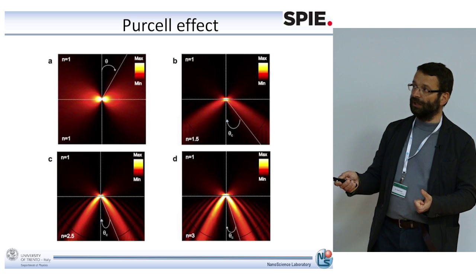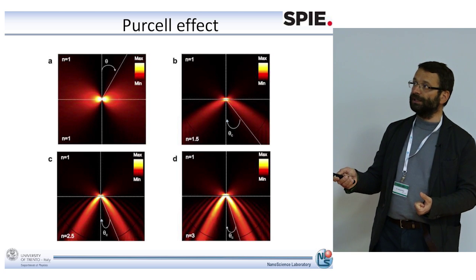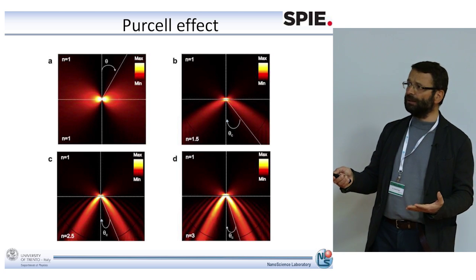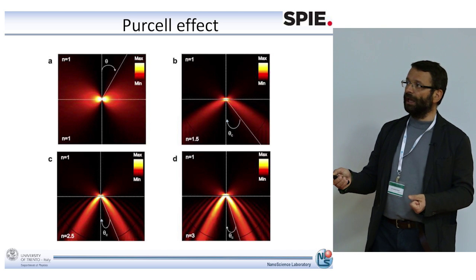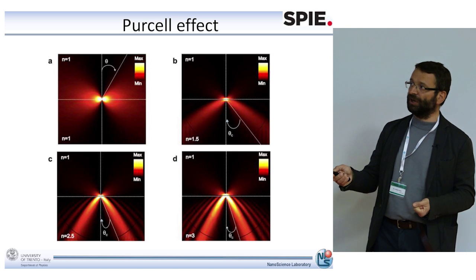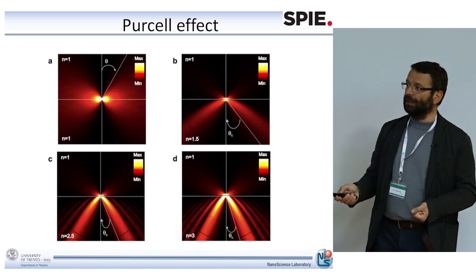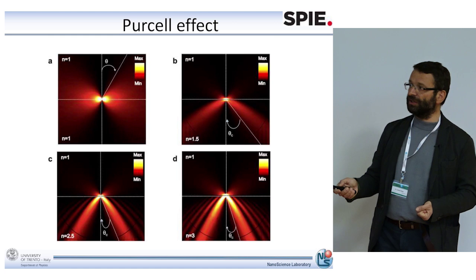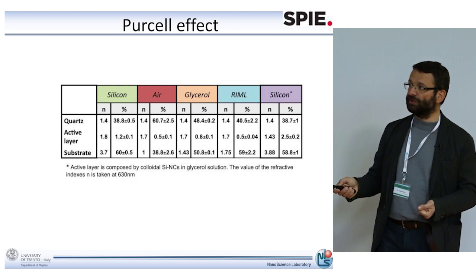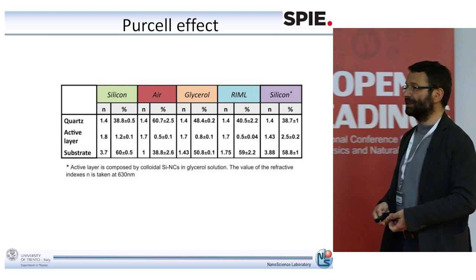And what you see here is indeed that. This is vacuum, n equal 1. Here is a liquid, glycerol for example, n equal 1.5. And you see that the light is preferentially emitted to the bottom. And if you increase the refractive index, more and more light is emitted to the region where the cell is.